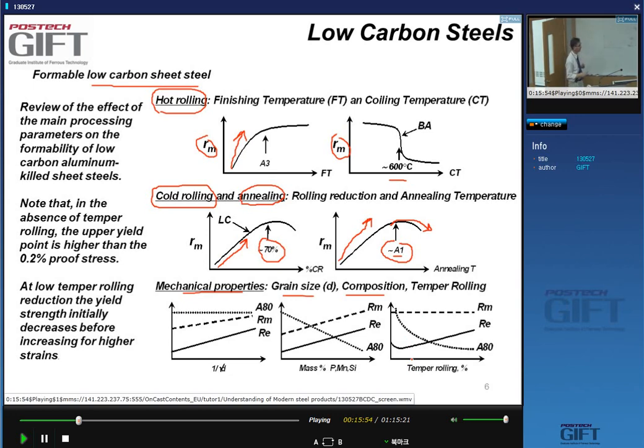When you temper roll, you remember that's the rolling you do after annealing, right? So after annealing, again, a low carbon steel, you're left with some carbon and nitrogen in solution. So these give me this Luder's elongation. By temper rolling it, I remove this. However, what I do is I deform the material.